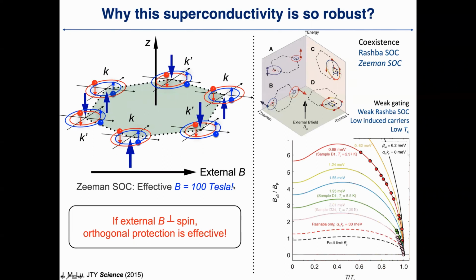And then with this very large field, if we apply an external field along the in-plane direction, this external field has to compete with this 100 Tesla. So if we have the Zeeman SOC involved in the paramagnetism, then this is very well protected. This orthogonal protection between the applied field and the K and K prime points is the reason for this very large upper critical field.